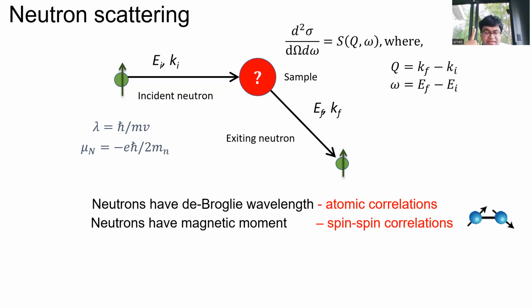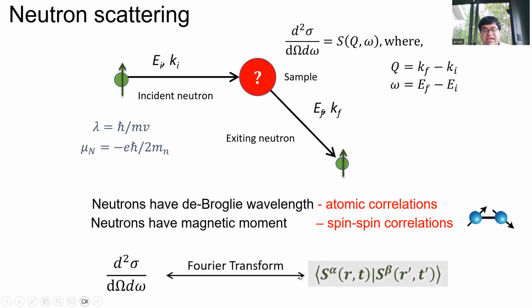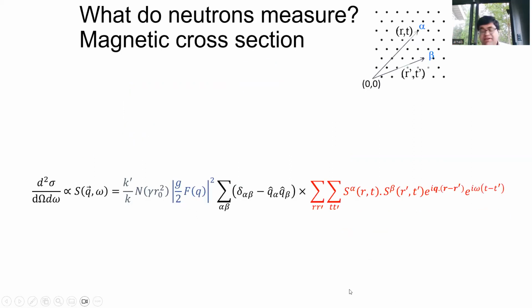So it does create a spin 1 excitation, and the propagation of the spin 1 excitation is something that you can check. So it can give you the spin-spin correlations very nicely, and the dynamic spin-spin correlations very nicely. And so what you get as the intensity is basically the dynamic scattering cross-section, which if you Fourier transform, you get the spin-spin correlation. In fact, if I write out the whole equation completely, this is the dynamic scattering cross-section, and this has this big equation here, but let me break it down for you.